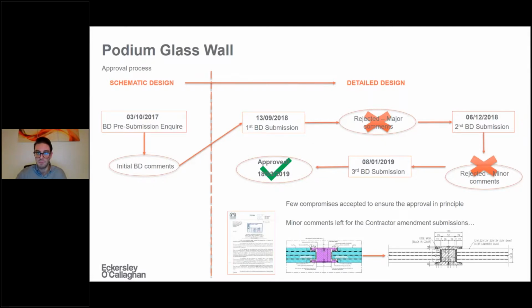So one of the compromises that we had to accept was the one on the clamp between the glass and the rod, which was not allowed to be recessed and therefore having everything flush with the glass. Although the brick models were proving that the glass was okay, also the central glass was able to transfer the tension and the shear transfer between the plies, we had to basically have a clamp from outside, and therefore we had this minimal build-up, minimum depth on top of the glass thickness.